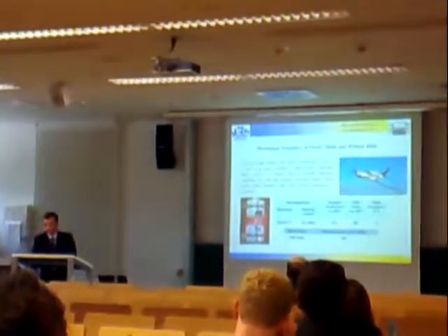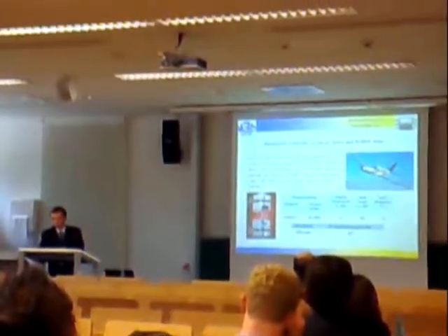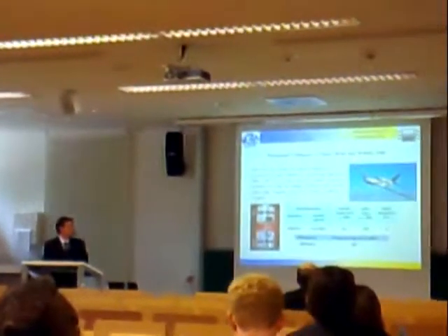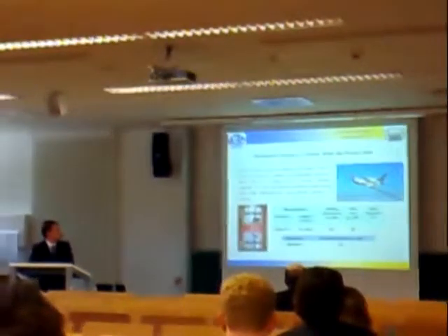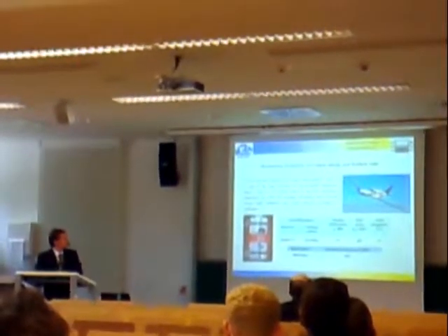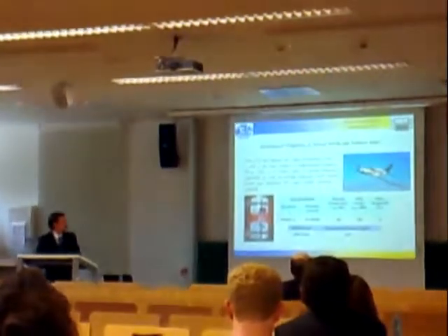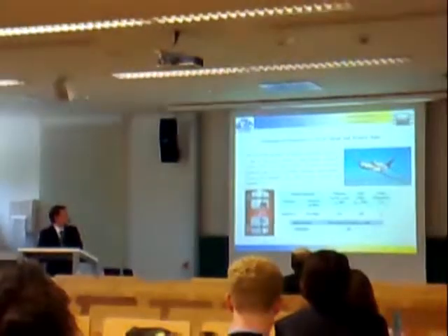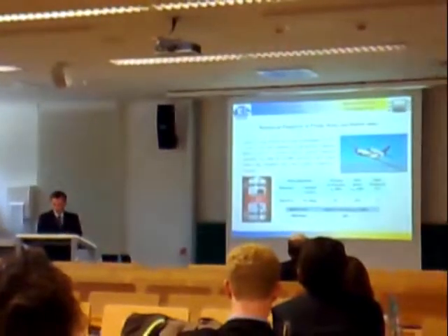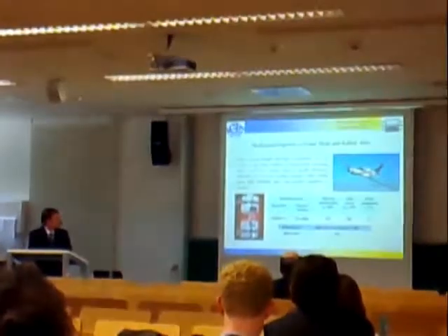Investigations were performed for welded joints of aluminum alloy 2024. This alloy is considered hard to weld with conventional fusion welding technologies. Due to its high strength and fatigue performance, 2024 is one of the most common high-strength aluminum alloys. This alloy is widely used in aircraft structures, especially for wing and fuselage structures, and in tension where high durability and crack growth resistance is essential. Here you can see basic mechanical properties of base material and welded joints.